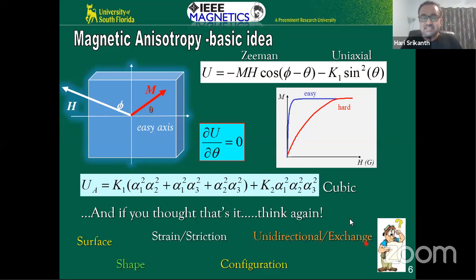Last but not the least is what is called unidirectional or exchange anisotropy. You may have heard of the term exchange bias. It's a very important term in spintronics. Those of you that are familiar with spintronics know this is spin-based electronics. So essentially, in this case, typically you take a ferromagnet and an antiferromagnet and you make a sandwich. Then the interface energy is governed by the interaction between the antiferromagnetic spins and the ferromagnetic spins at the interface, and that results in the so-called exchange coupling or exchange bias. It results in the shape change of the hysteresis loop and also a shift in the hysteresis loop.